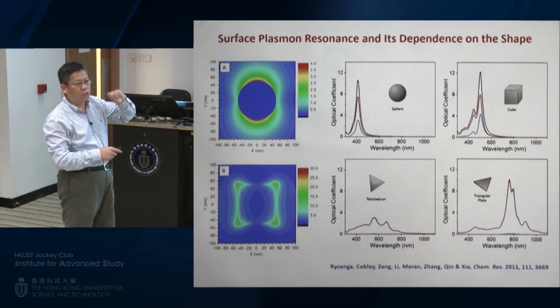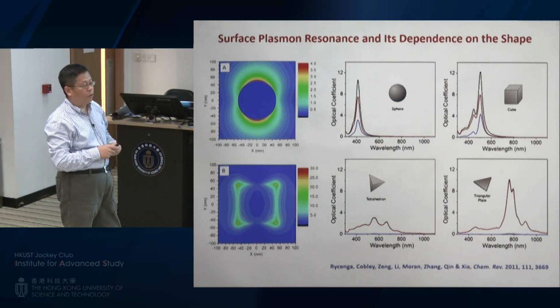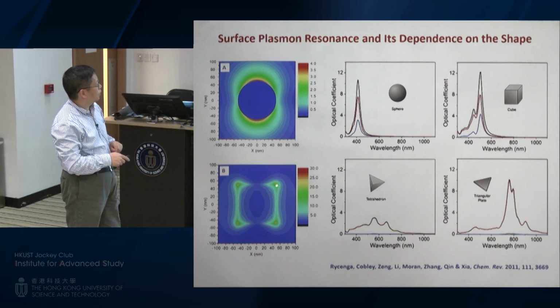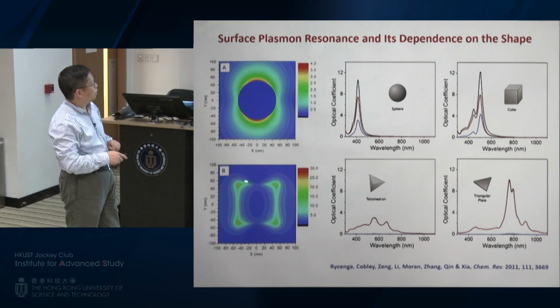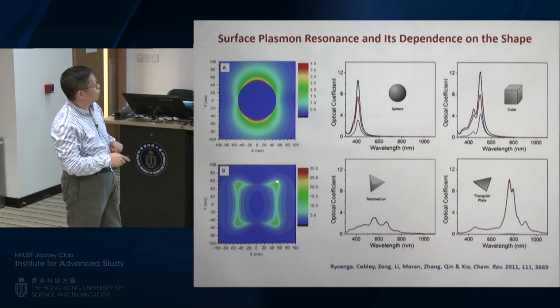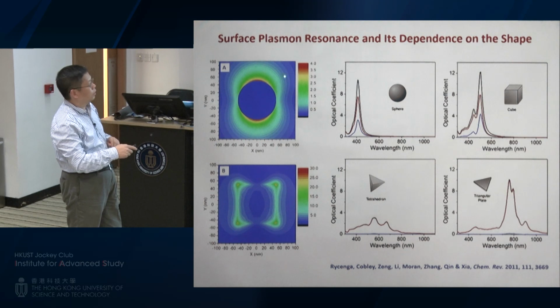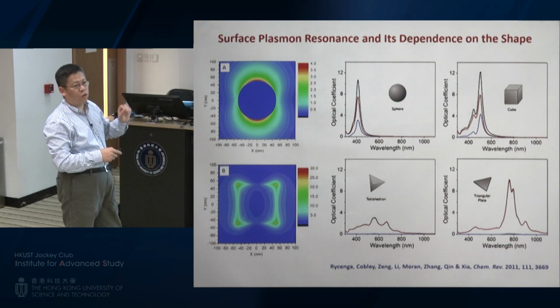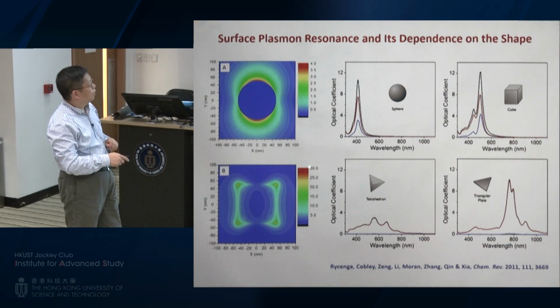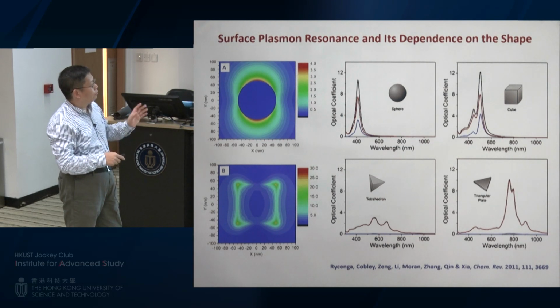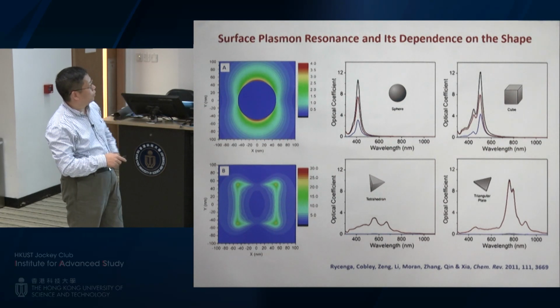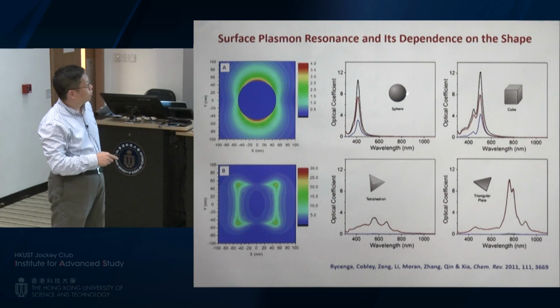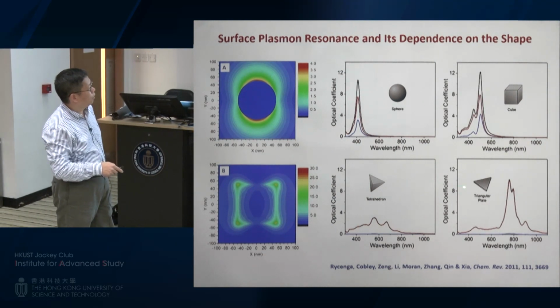So it's about almost 10 times difference. And if you put the molecules at these corner sides, their Raman scattering cross sections could be increased by almost like 10,000 times relative to this one, because it's proportional to the electric field raised to the power of 4. Anyway, the message I want to deliver over here is that we can control the shape of these kind